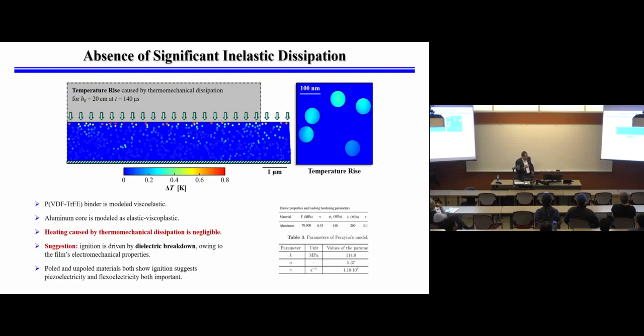I'm not going to go into the details. But first, some people might automatically think that if you apply a mechanical loading, maybe you're generating a lot of plasticity or viscoelasticity that gives you the temperature increase. We did simulations to show that there is very little temperature increase due to viscoelasticity or viscoplasticity in the material. It's not mechanically driven, it's electrically driven, is the point.